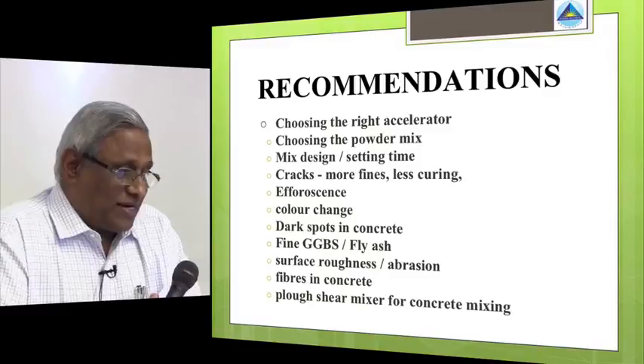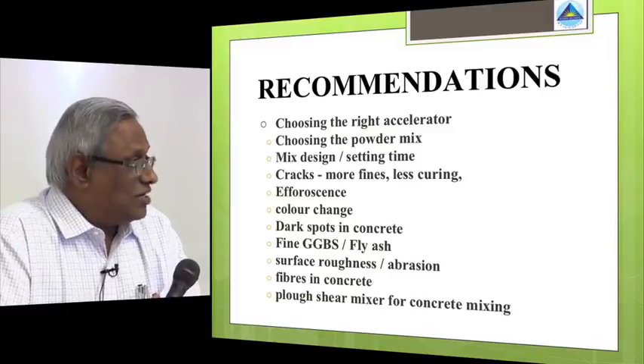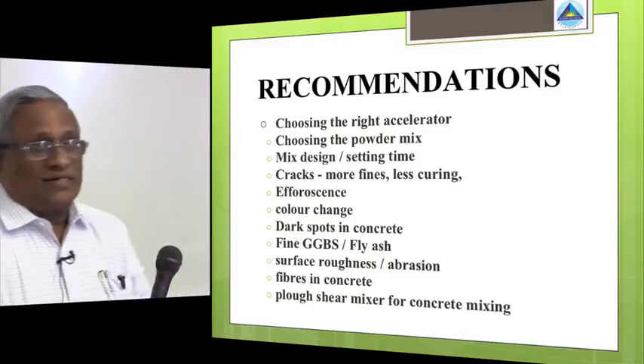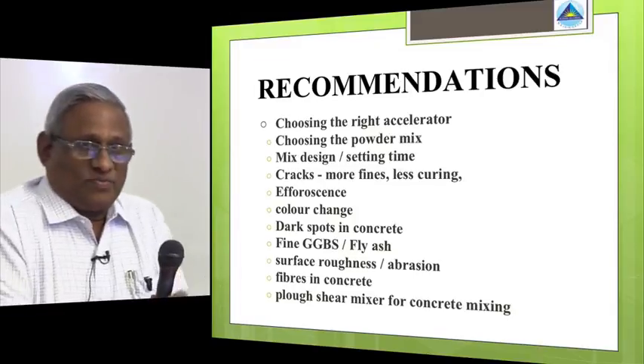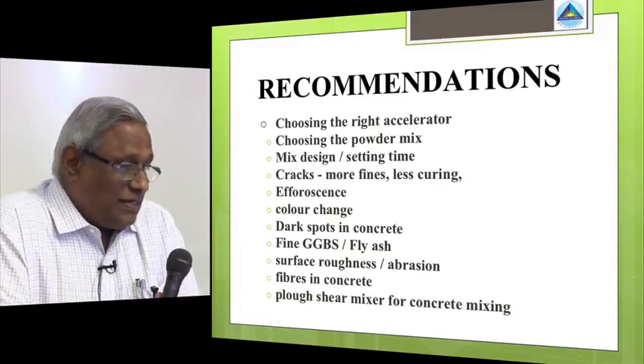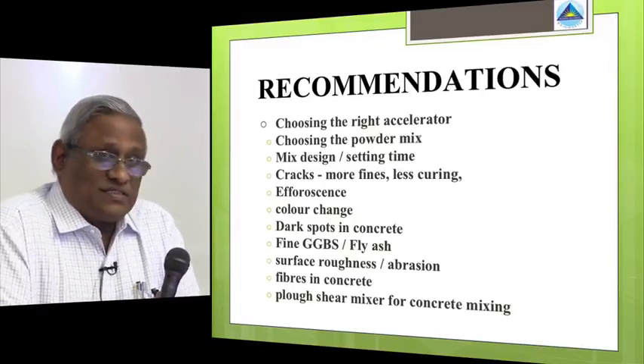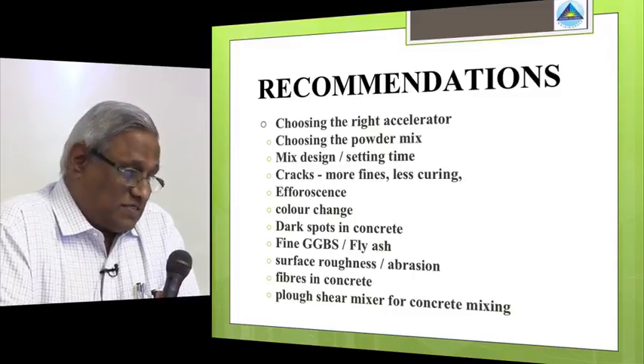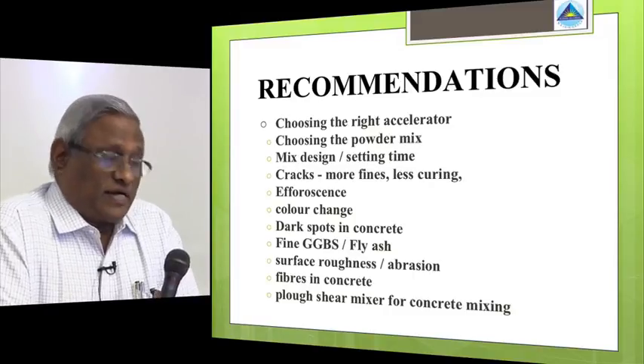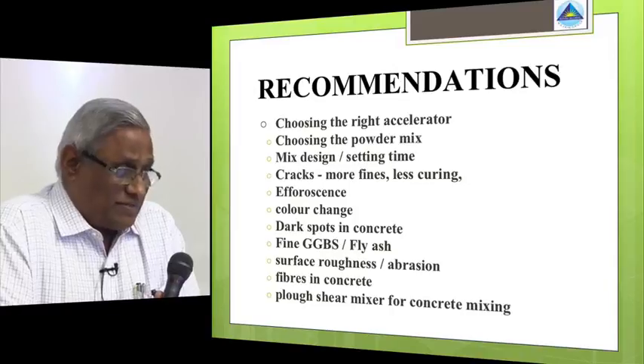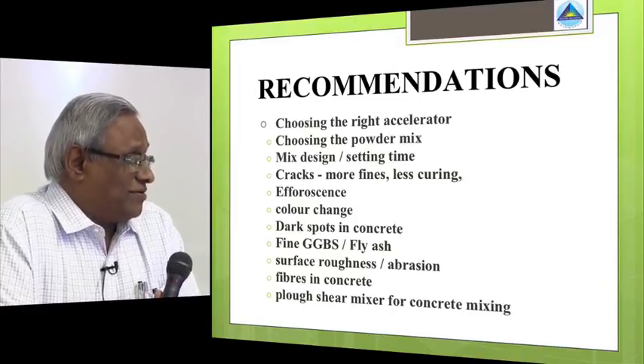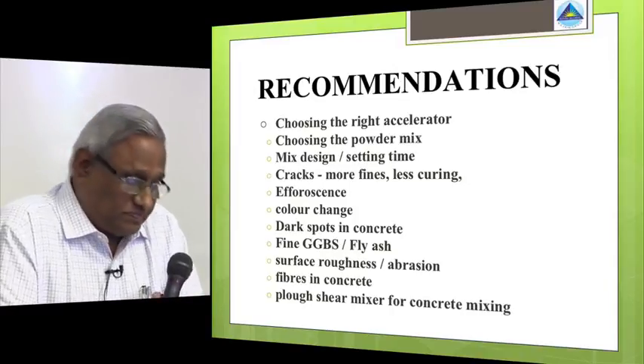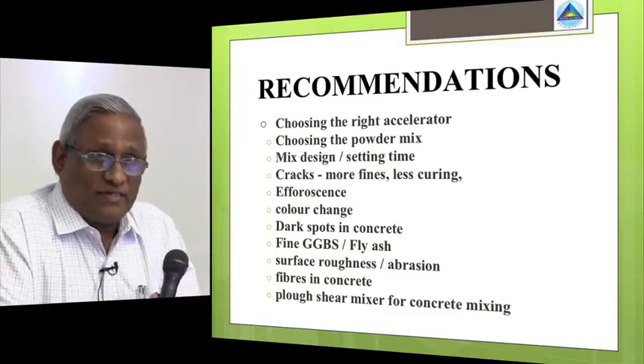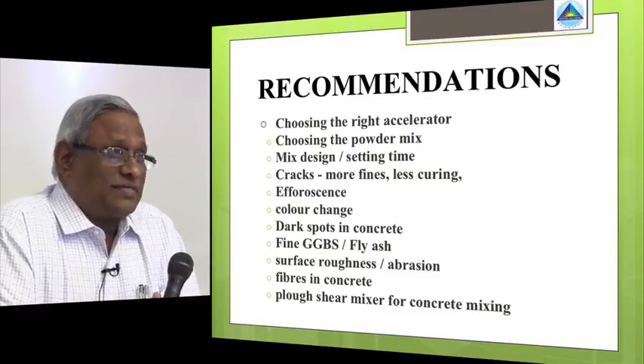The cracks will come. Cracks are not uncommon in concrete. But how you address them is more important. Sometimes you have more fines and it develops cracks, and if it is under-cured, I know there is no curing, but still there is a curing of geopolymer concrete. It cures within. If you demold it earlier, then it develops cracks.